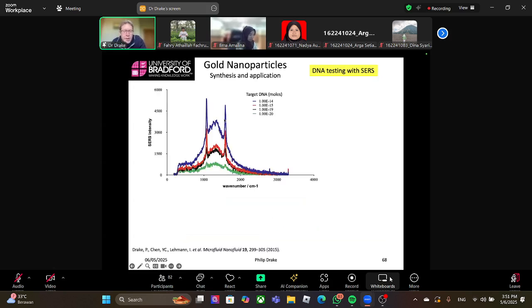And using that system, again, we see the same two peaks. It's still mercaptobenzoic acid labeled gold. And we can link these peak heights to the concentration of DNA, where you get a linear dependence between SERS peak intensity and DNA concentration.